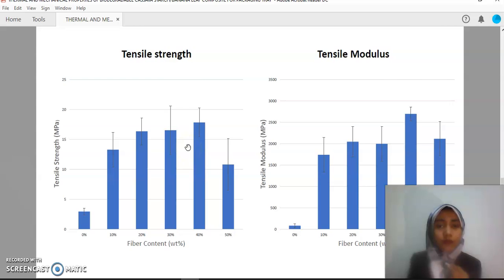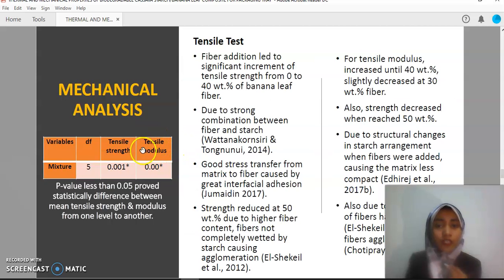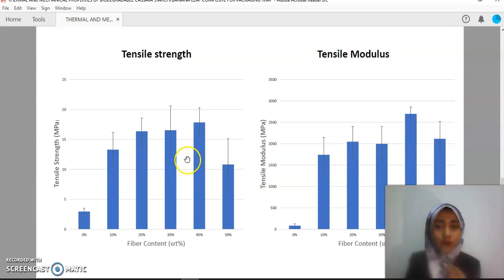Why do I say significant? Because I ran the ANOVA analysis, and it showed a p-value less than 0.05. So it proved that the mean tensile strength and modulus are statistically different from one level to another. The significant increment is due to the strong combination between fiber and starch. A previous study also says it is due to good stress transfer from matrix to fiber, caused by the great interfacial adhesion. However, at 50%, the strength reduced.